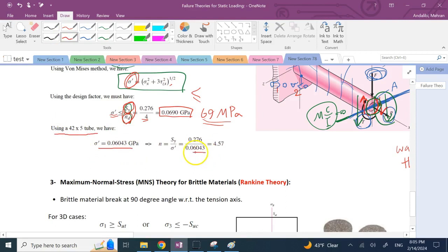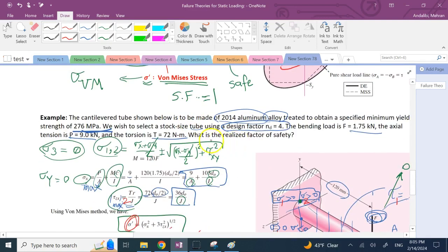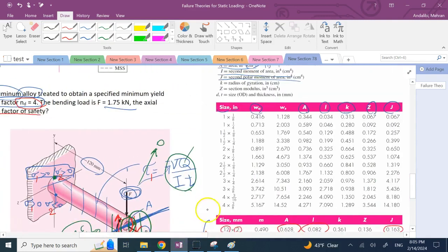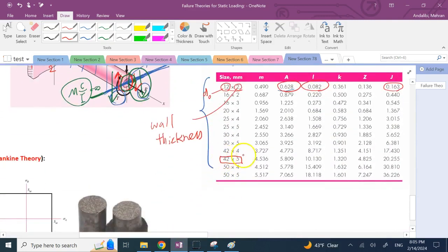And if that's the case, then your real safety factor N is going to be 276 megapascal divided by 60 megapascal. It's going to be 4.57 instead of 4. Okay, so your realized or actual safety factor is going to be more than what you wanted, because you have what? You have a little bit more thickness of material than you want. But you might not go to this. If you go to this one, your safety factor will fall below 4 here.